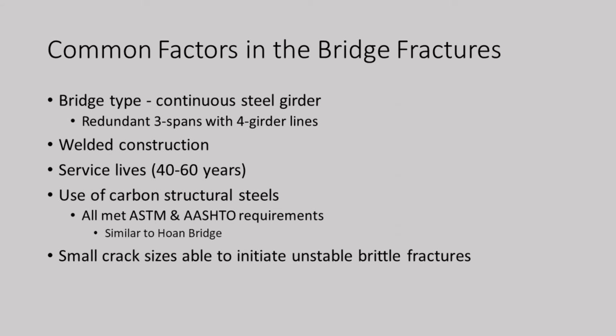They all used carbon structural steels, and all of those steels met current ASTM and AASHTO requirements, and I should say so did the Hoan Bridge back in 2000. The other thing we see is that small crack sizes seem to be able to initiate unstable brittle fractures that can basically part or almost part these girders.